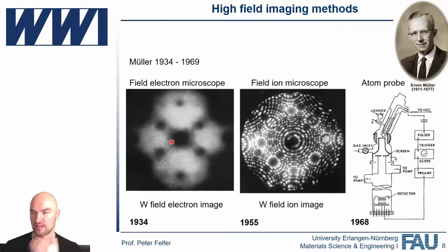So when the electrons come out of the surface, they have a very low energy. So their position is very undefined. And this is the limitation to a resolution of about 2-ish nanometers. Yes, it's close to atomic resolution, but not quite.